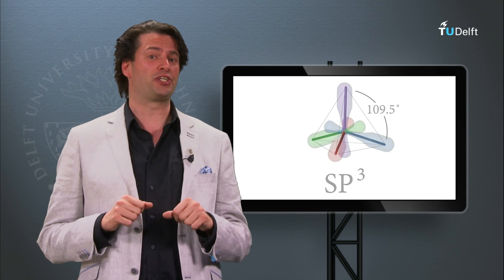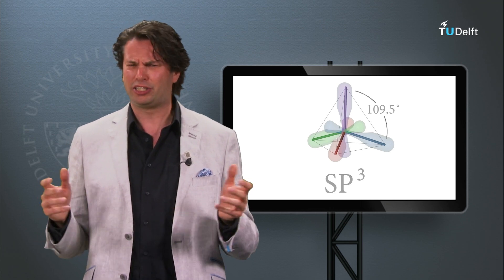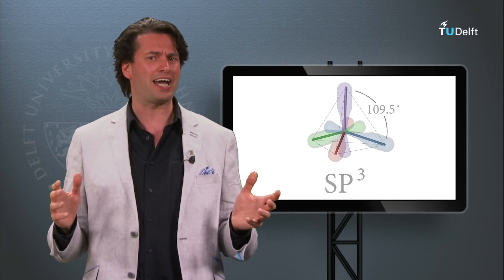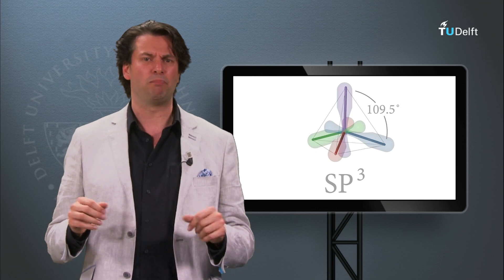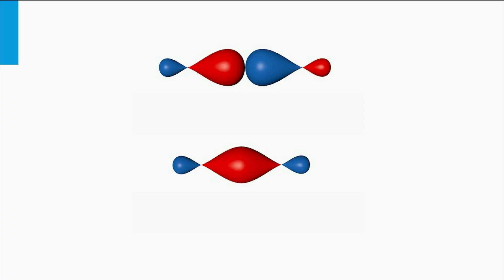Now we can roughly understand the coordination of the lattice of crystalline silicon, but we still don't understand the origin of the band gap. For that, we have to look in more detail at how a bond is made between two atoms. Here you see two sp3 orbitals of two neighboring atoms which are at a far distance from each other. Both orbitals have one electron at a discrete energy level that resembles that of the sp3 hybrid. To establish a bond, the two atoms have to approach each other — the orbitals start to overlap and merge into one molecular orbital with its own shape.